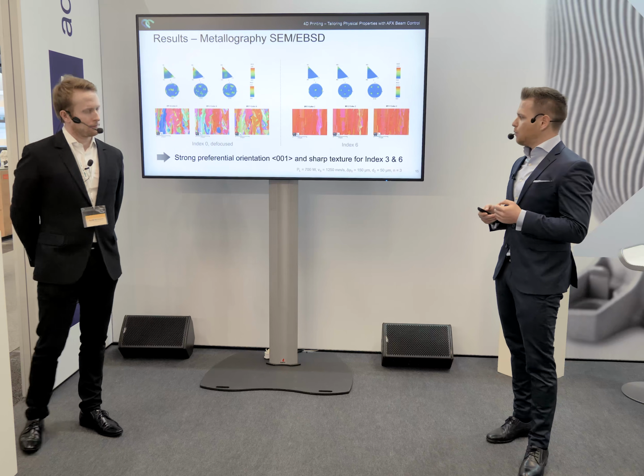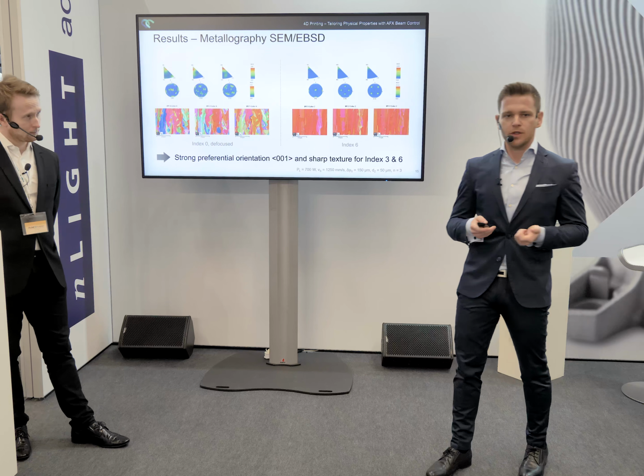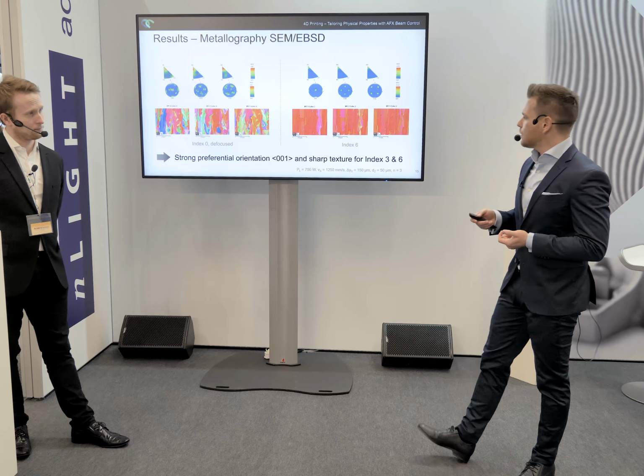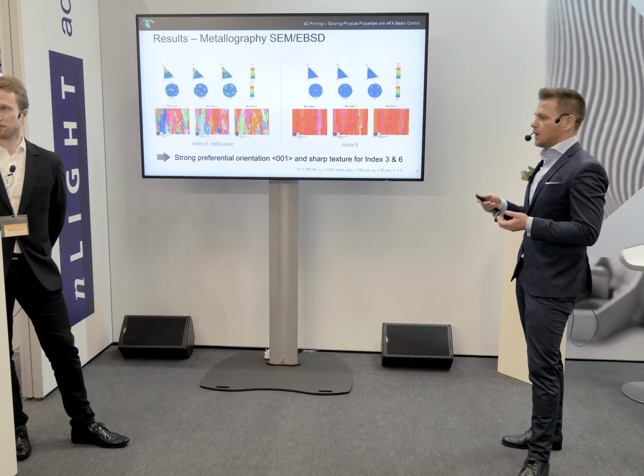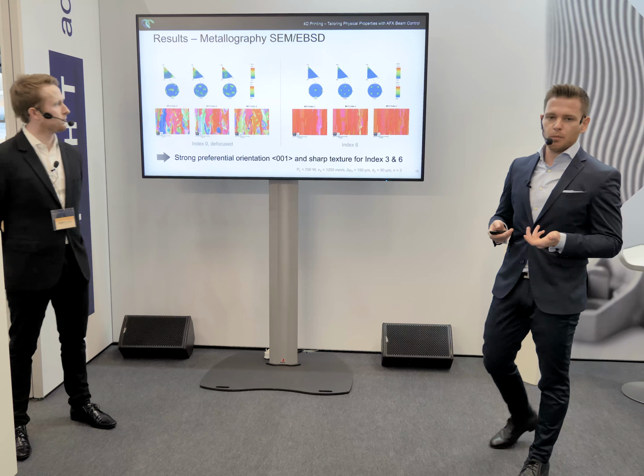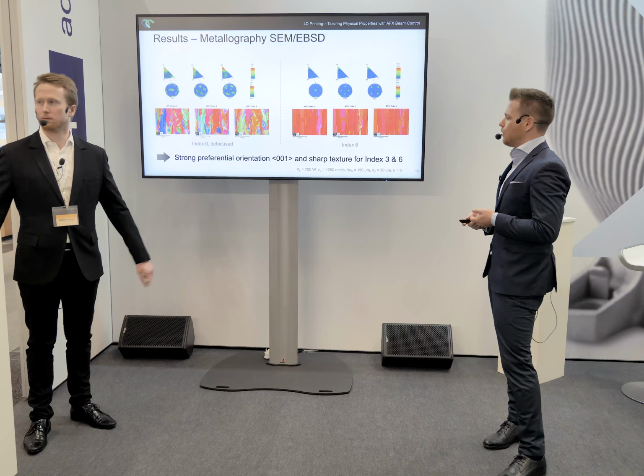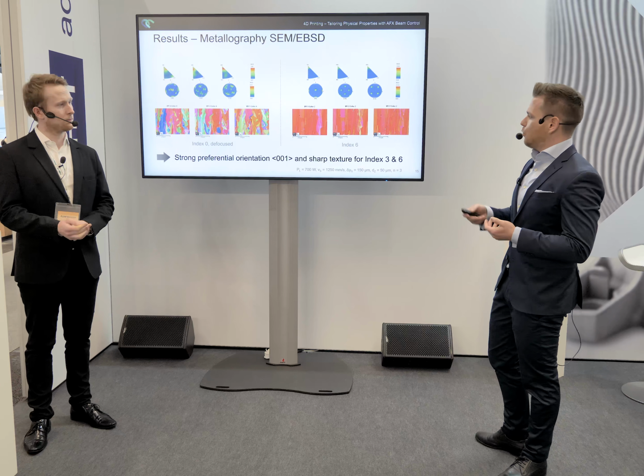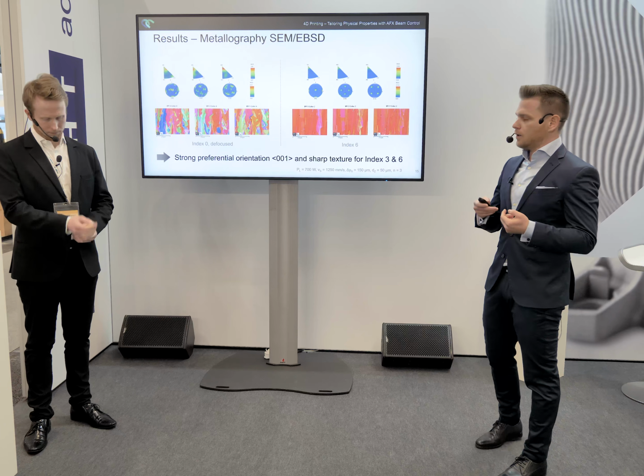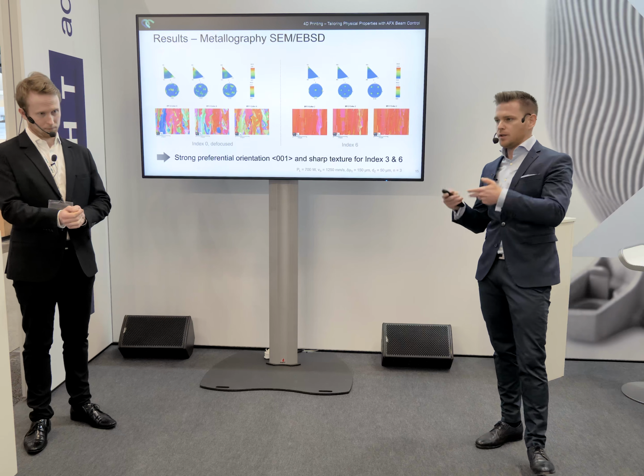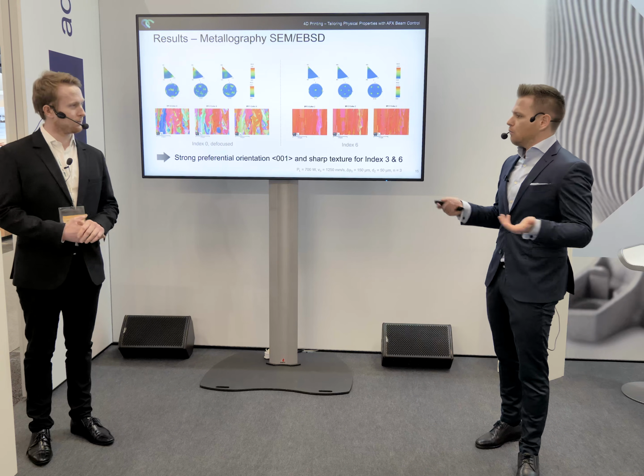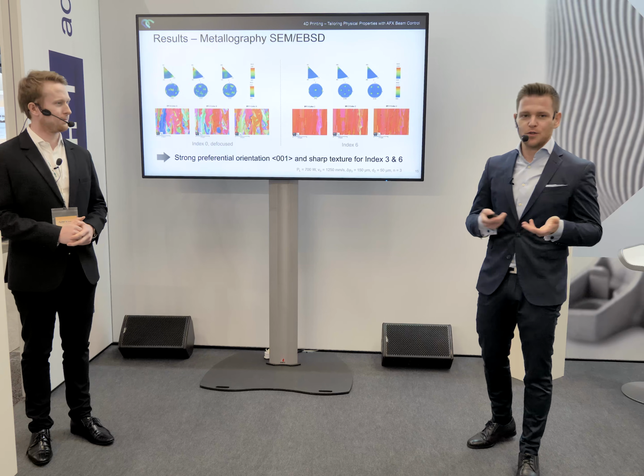And since grain boundaries are invincible obstacles for dislocation, dislocation movement is favored in the case of index 6, leading to a higher plastic deformation and thus a higher elongation at break. So we can explain the differing mechanical properties by the texture. And now the question is, why is this texture so different?